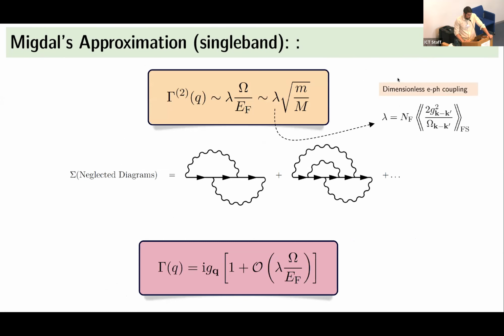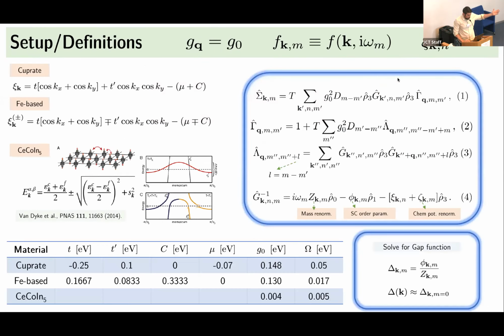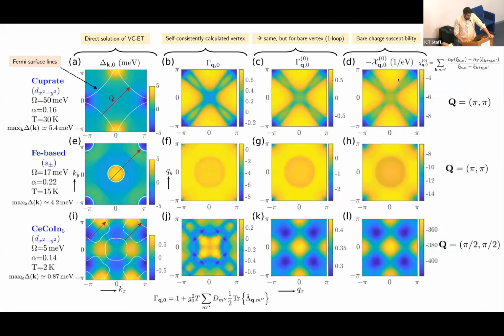So in Schrödi et al., they set up the problem quite nicely, and they wanted to solve the Eliashberg equations for some simple Holstein model, but they included some material specifics, namely a bunch of unconventional superconductors simply projected into the problem using an effective tight binding picture to capture the nested Fermi surface in each of those materials. So there's a cuprate, iron-based, and a heavy fermion superconductor. And they get these unconventional pairing symmetries, including a D-wave pairing symmetry.